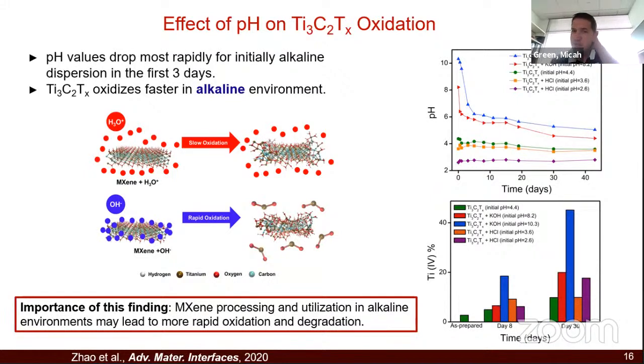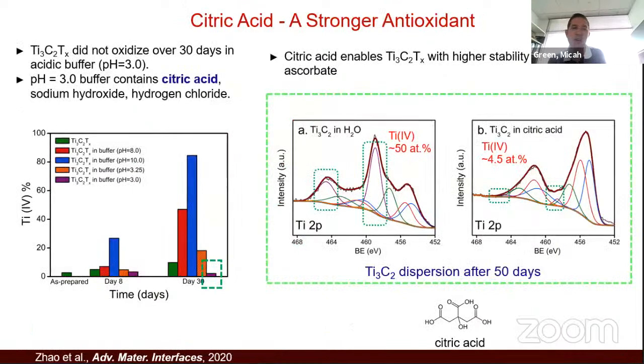Since then, we've also looked at the effect of pH. Basically what we're seeing is that if you use an alkaline environment, these things oxidize a lot faster. And as the MXene oxidizes, you can actually change the pH environment in the dispersion itself. So noting what the pH is of your dispersion can affect how rapidly that happens. We've also found out that citric acid, another common kitchen item, is a great antioxidant for protecting MXenes against these kinds of degradation processes.